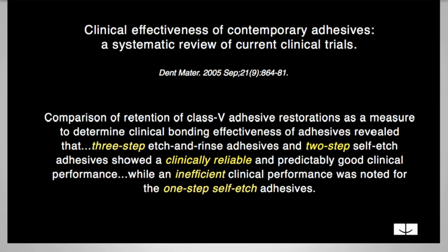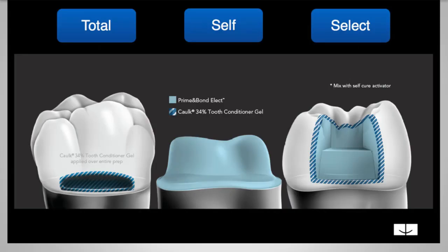Now, Dentsply came out with this kind of guide, and I thought it was actually very good. And so it shows where to use total etch and where to use self-etch. So here, total etch in these types of situations, class 5s, you can use total etch everywhere. In a class 2 restoration where there's a lot of dentin, you can use just a select etch, just using the phosphoric acid etch on the enamel here, and then using your self-etch inside the box. And when you have no enamel present, well, that's a good time to use the self-etch.